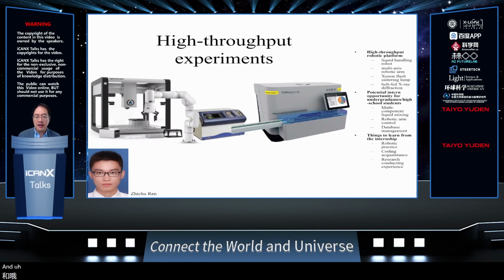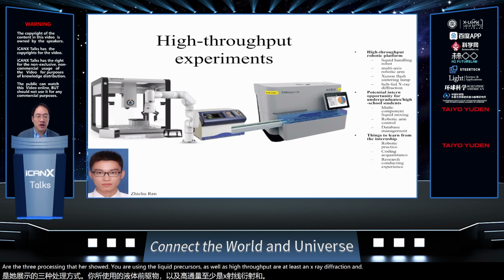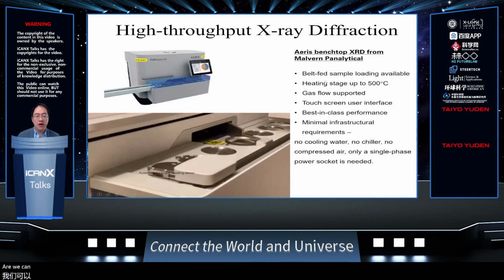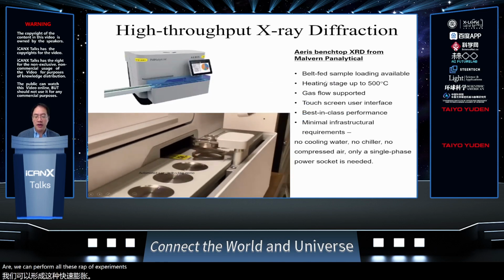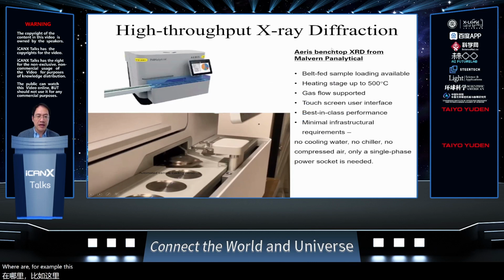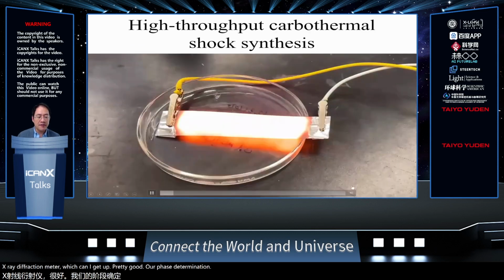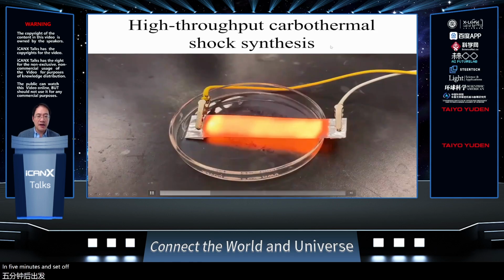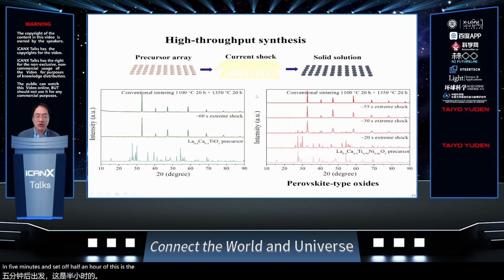And in the last few years, Zhichu has taken this further, by using this liquid robotics combined with the extreme processing that I showed you, using the liquid precursors, as well as high throughput X-ray diffraction and electron microscopy. We can perform these rapid experiments where, for example, this is an X-ray diffractometer which can get pretty good phase determination in 5 minutes instead of half an hour. This is the high throughput carbothermal shock.